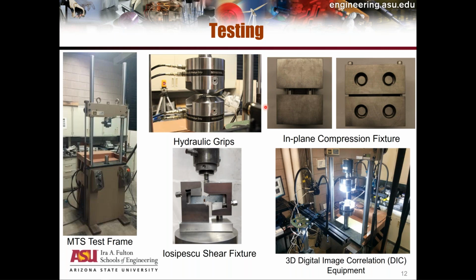So these are a number of fixtures available to test the specimens in tension, in compression, in shear, and we can do these simple ASTM type of tests or more complex tests for which there are no ASTM standards. And we use digital image correlation to get full field displacement field that we then convert into strains, and we use that to find out the stress strain curves and other properties of interest.